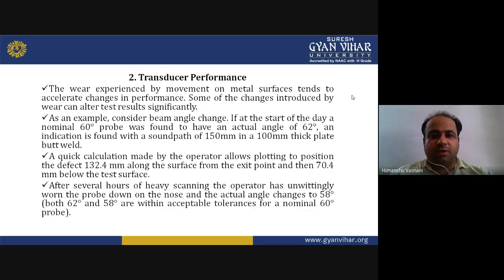The wear experienced by movement on metal surfaces tends to accelerate changes in performance. Some of the changes introduced by wear can alter test results significantly. As an example, consider beam angle change. At the start of the day, the nominal 60-degree probe was found to have an actual angle of 62 degrees. An indication is found with a sound path of 150 mm in a 100 mm thick plate. A quick calculation by the operator allows plotting the position of the defect at 132.4 mm along the surface from the exit point and 70.4 mm below the test surface.